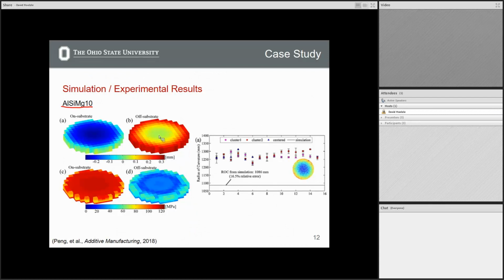If you look at the very bottom, this is around 0, all the way up to 0.3 millimeters distortion you get in the part once you relieve it. The stress is the opposite case. When it's on the substrate, it's essentially in the highest stressed configuration, and then you take it off the part, and the stress relieves considerably.